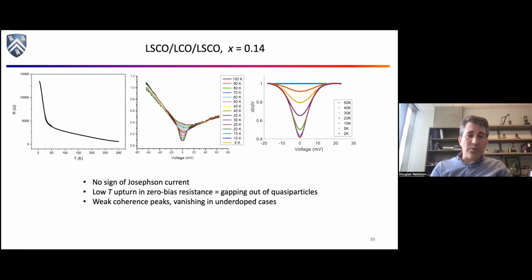So let me show you actual data, right? We're at like the 45-minute mark in the talk. I'll show you actual data. So this is electrical resistance versus temperature of one of these copper oxide devices. And what you see is, as you cool it, it becomes more insulating, okay? That's because you got that insulating spacer in there. And then when you get to really low temperatures, this is in Kelvin, it really becomes a lot more insulating.